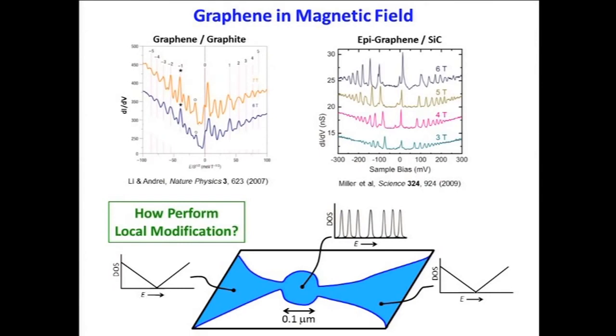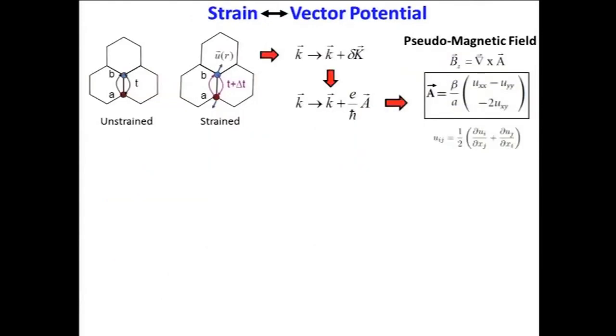But with graphene, this kind of experiment is sort of possible, because graphene has a very peculiar property, which is that if you strain it in a particular way, then the electrons in graphene will behave as though there's a magnetic field turned on. They're going to want to go around in circles. And that's a very peculiar effect. I don't know any other material that has this effect. And so I just want to spend a minute or two trying to give you a hand-waving explanation of why graphene has this really interesting behavior, that when you strain it in a particular way, it behaves as though there's a magnetic field. And we call that a pseudo-magnetic field.